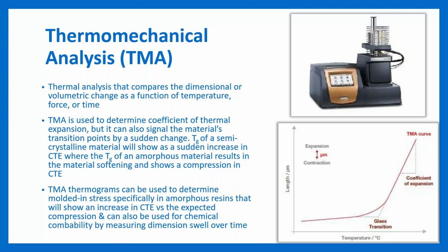It's also the other reason, if you've dealt with it much or you've done much with it, when you ask us, and then in turn, we ask our suppliers of the material that they make, if you're asking us for the CTE or CLTE, we generally want a range because as you can see, it changes based on the thermal transition of that material. So we want you to tell us what range you're looking for that information within. And that's where we can go and find that on average, the change.